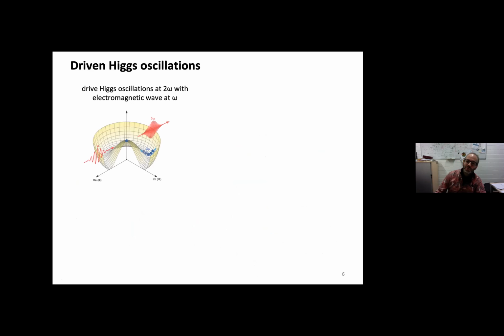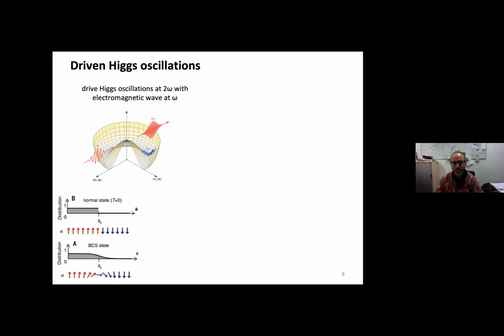A second possibility for exciting or controlling Higgs mode in a system is now not to make a quench of the potential, but to go to the system with a low frequency terahertz pulse that is below the superconducting gap. So in the linear regime, we have no excitation of quasiparticles. And then one can show that the superconductor will respond with a 2 omega response to this driving field. And then if these two come in resonance, then the superconductor emits a characteristic third harmonic in the system. And this physics one can understand in the so-called Anderson pseudospin model.